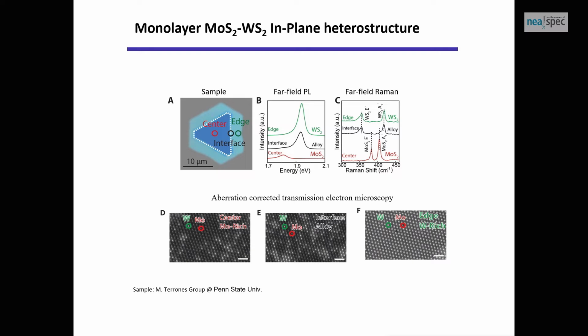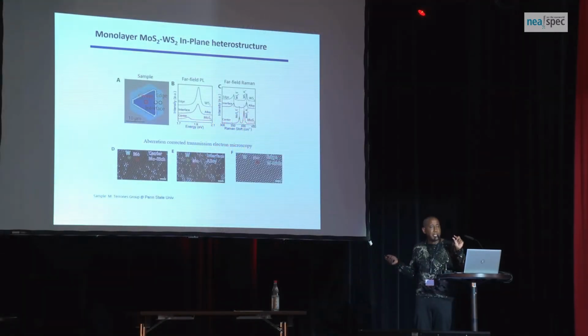It's an alloyed interface. It has both materials in it, and it's about 100 nanometers in width. So it contributes both from the oxidation or degradation point of view of this material, as well as its optical properties. It plays a major role in that. And the nice thing about this material is if you take a far-field PL spectra near the band gap of WS2 and MoS2, the two are nicely separated.